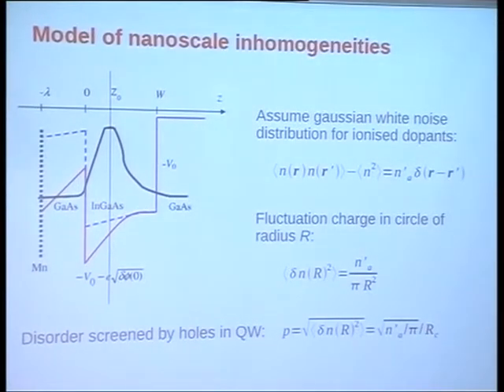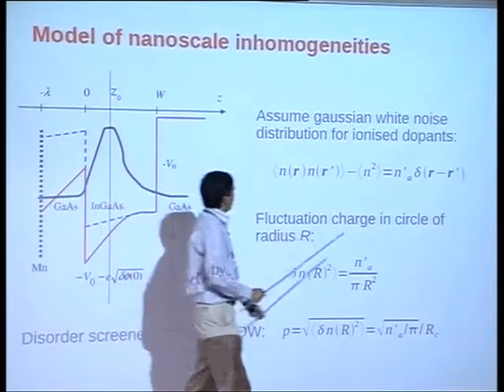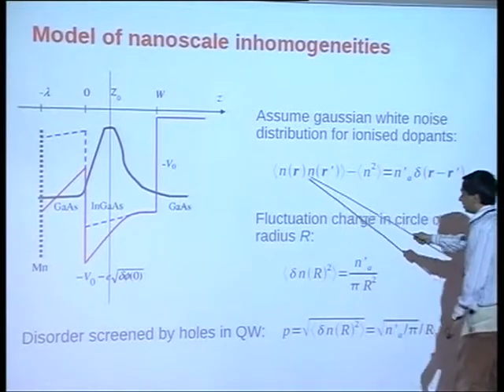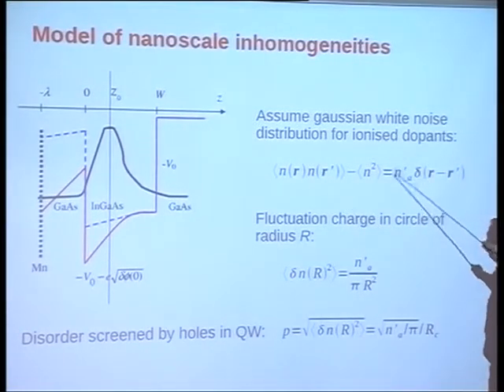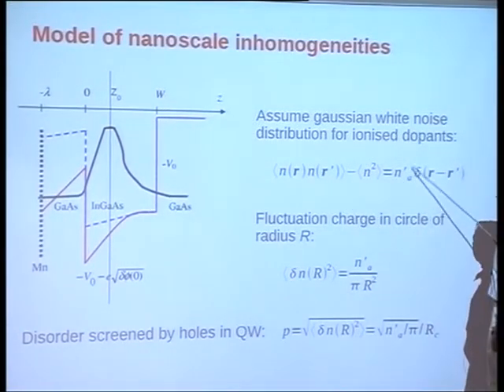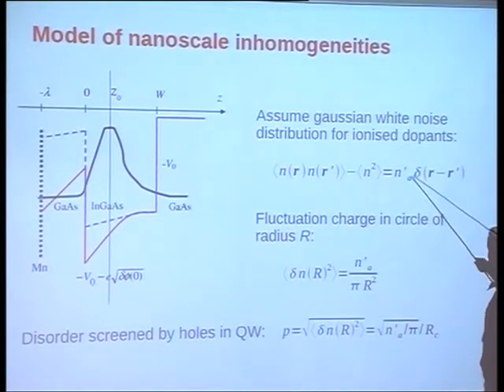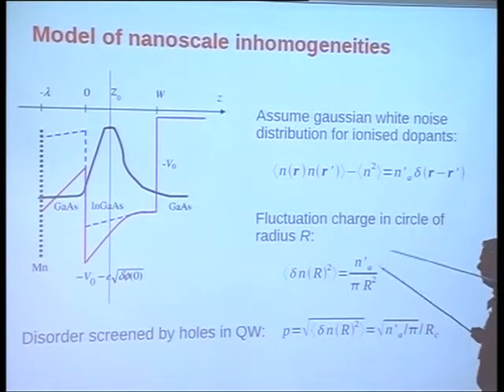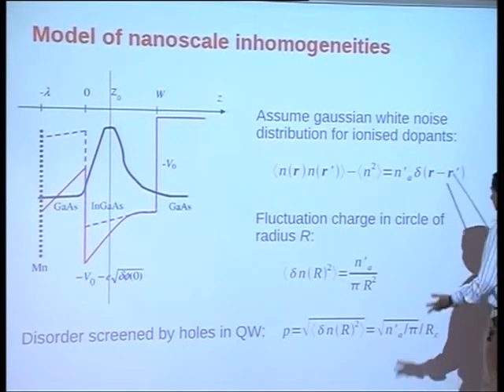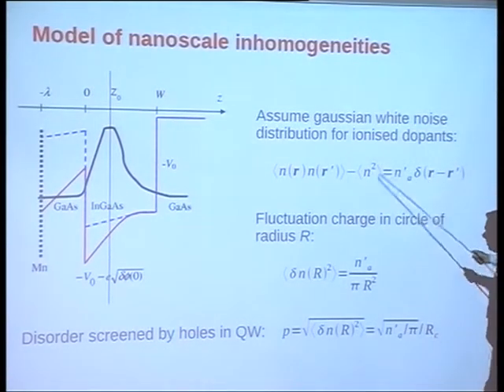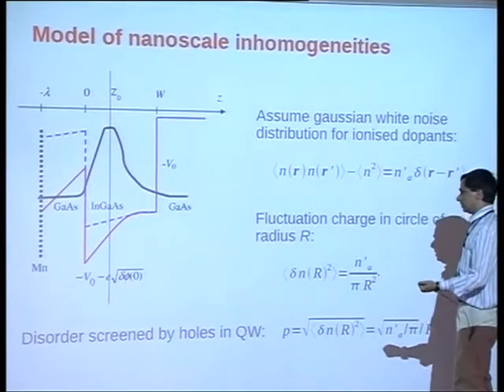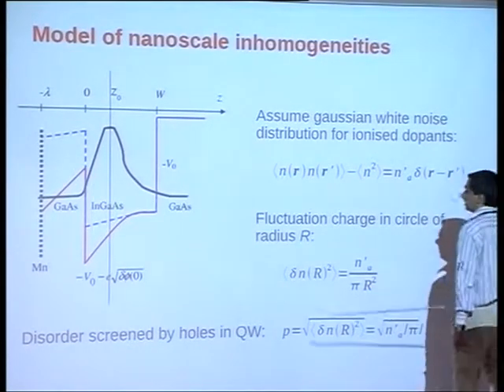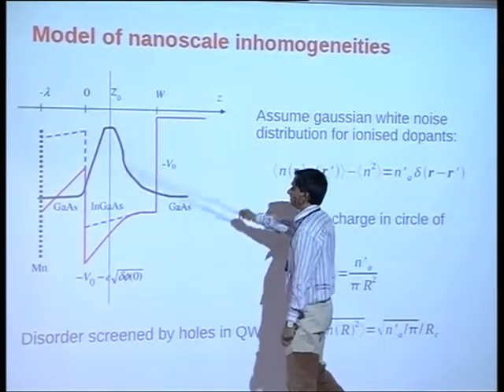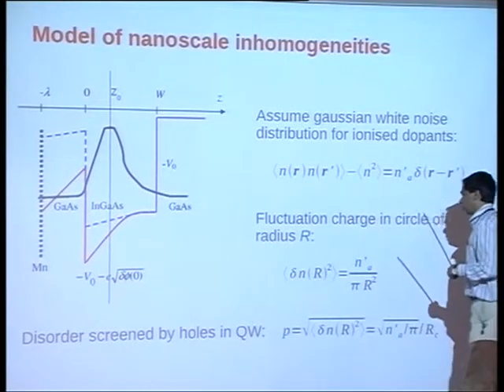So the modeling is as follows. We subtract off all backgrounds and absorb that in the average potential well, and then say that on top of that there are Gaussian fluctuations of the ionized manganese distribution, and we just assume this white noise distribution by fiat. Maybe better approximations are available, but this suffices for some simple-minded treatment for the understanding of charge inhomogeneities in the two-dimensional quantum well.